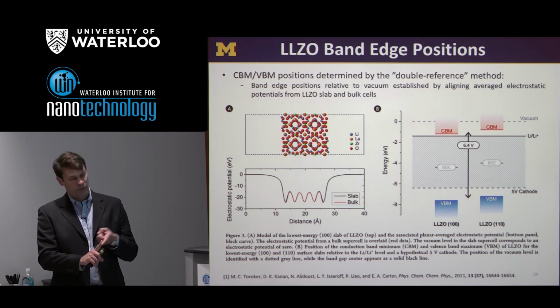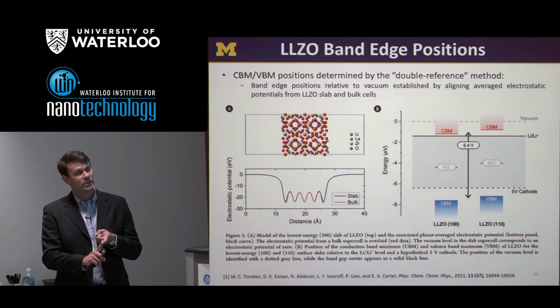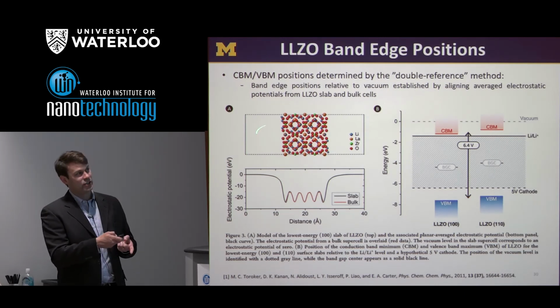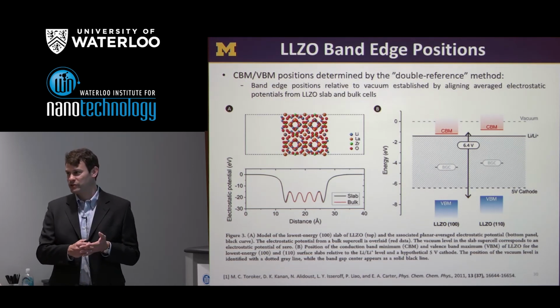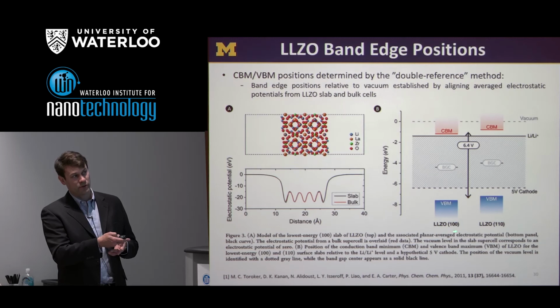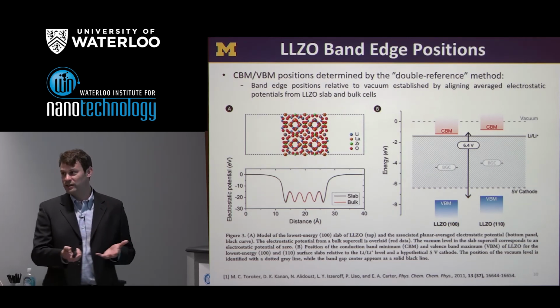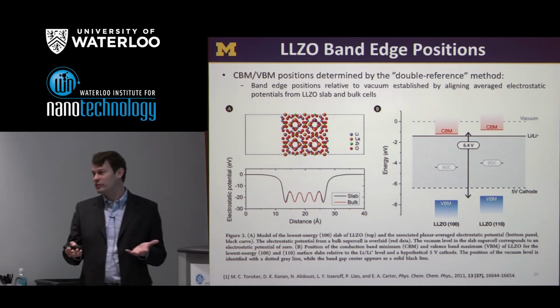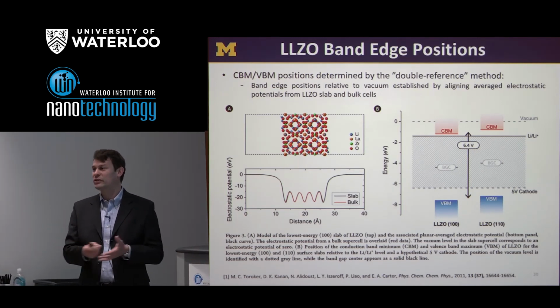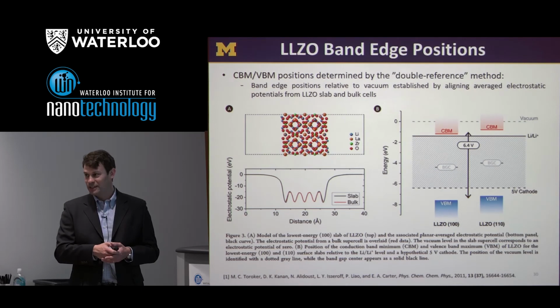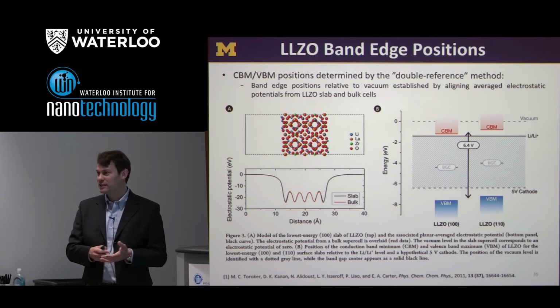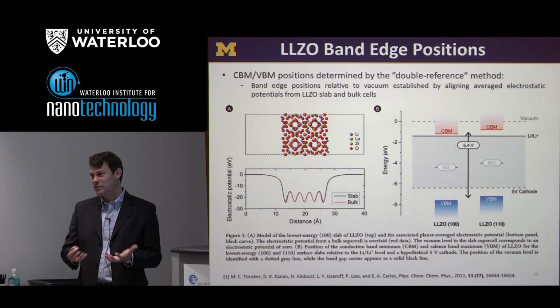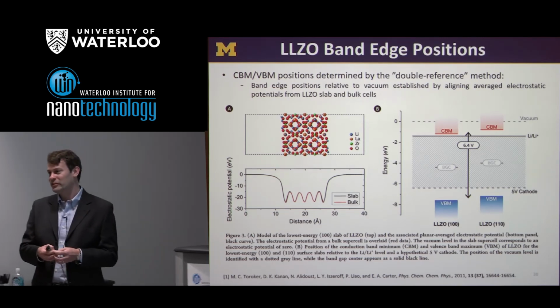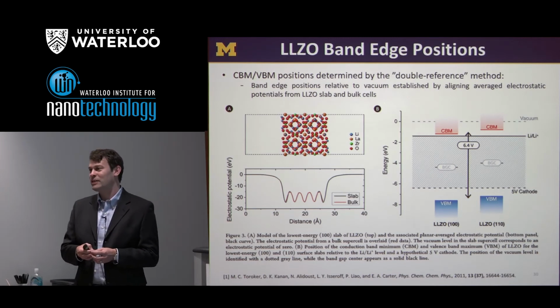Well, this is published, so we can discuss the details, but the slab calculation is done on the two lowest energy surfaces that we found, say within the 100 direction and 110 direction, assuming equilibrium with lithium metal. So there's 10 others that we found were not competitive and therefore presumably not realistic. And so we use the lowest energy models to get this average electrostatic potential. You would get a different answer otherwise. This is kind of like a work function calculation where the dipole of the surface will affect the work function. So our logic here is to use the lowest energy surfaces. We presume those are the most realistic and would give the best estimate of the electrostatic behavior.